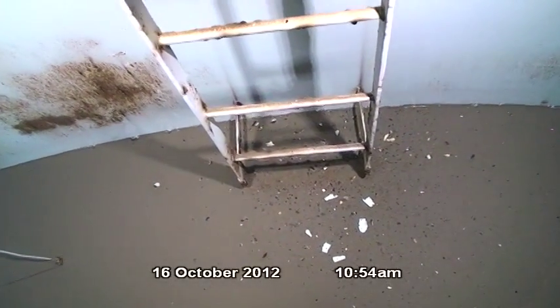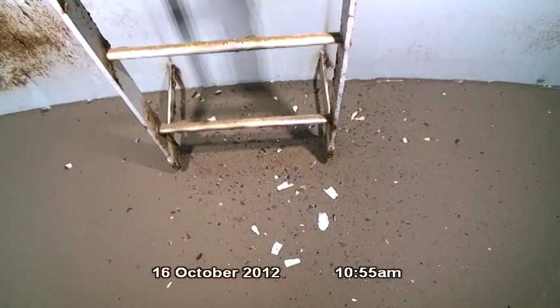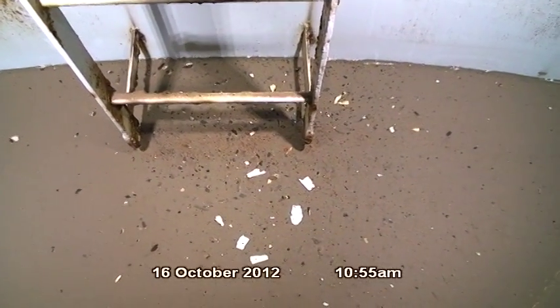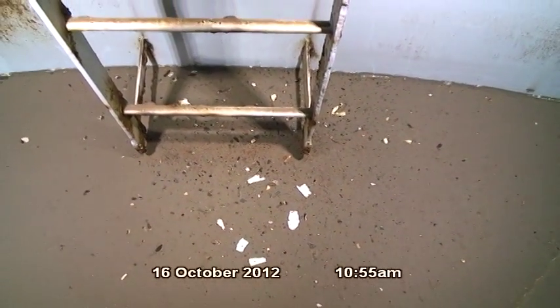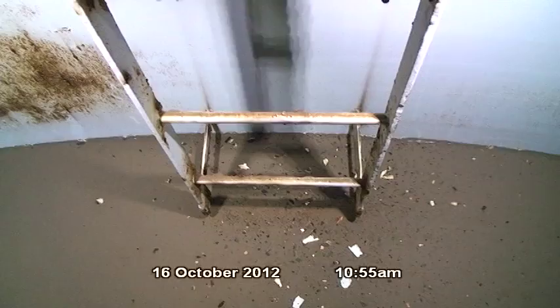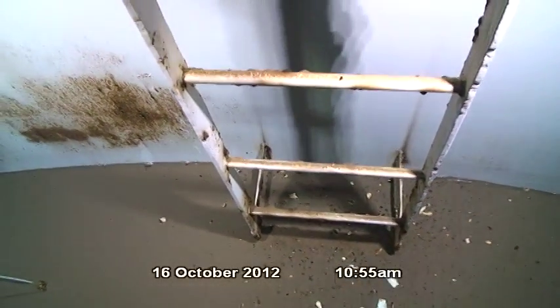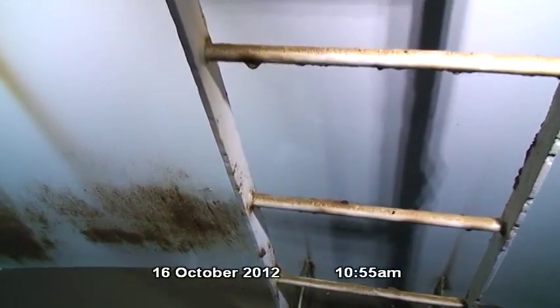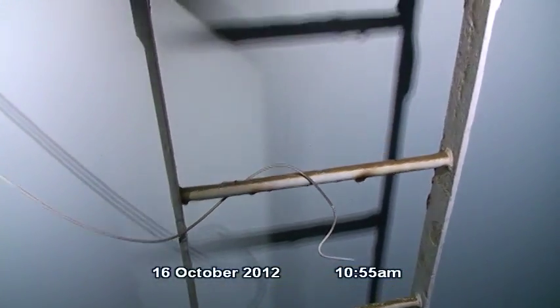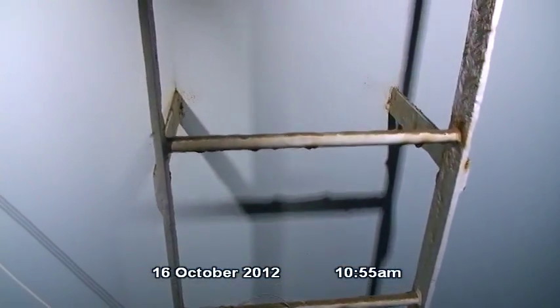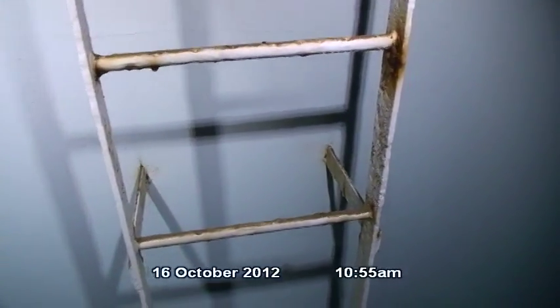We're now going to begin our interior inspection, beginning at the base of the interior access ladder. Small corroded metal flakes and delaminated epoxy coating are located on the floor beneath the ladder. The ladder is coated with epoxy. The epoxy coating on the interior access ladder is in fair to poor condition. Coating defects have resulted in corrosion ranging from light pinhole type corrosion to dense corrosion in approximately 100 areas on the ladder. The ladder does appear to be securely welded to the shell.